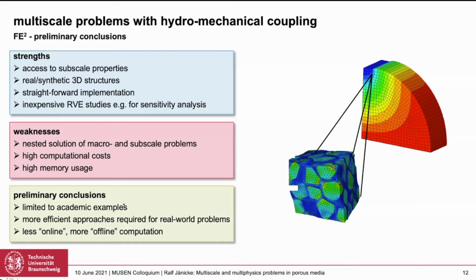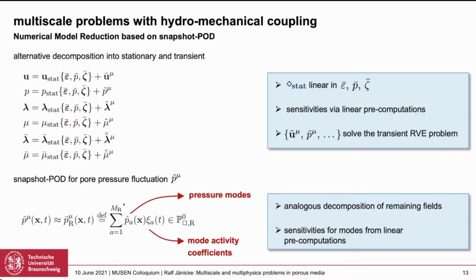The basic idea is, of course, it would be nice to have more pre-computation in an offline sense and less online computation, which is the expensive one. One way of doing that is numerical model reduction. I would like to present very briefly how we do that in this case, based on a snapshot POD, proper orthogonal decomposition. The first thing we do here, as I said, this example is not super complicated because it's transient but linear. We now introduce an alternative decomposition where we decompose all quantities into a stationary and a purely transient part, because the stationary part is linear. Linear is always nice, and it can be pre-computed.